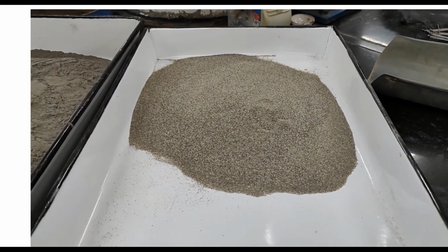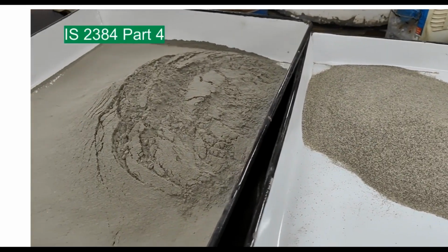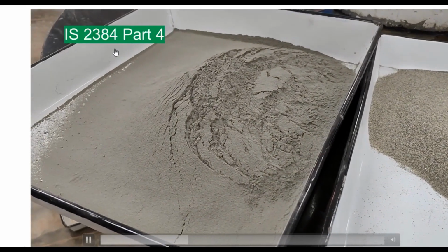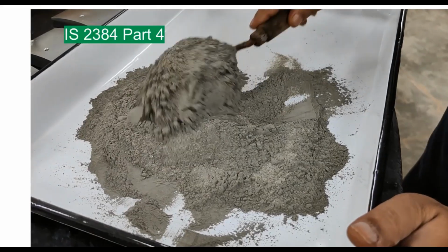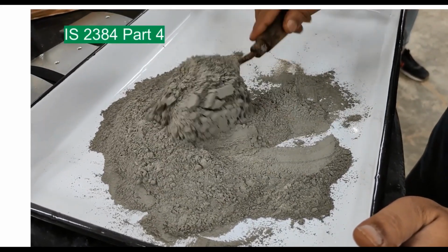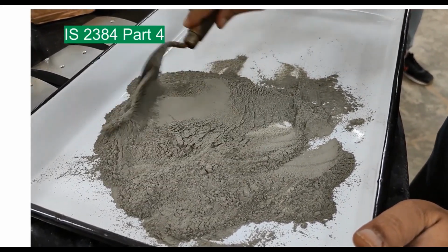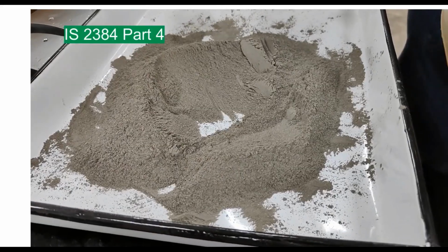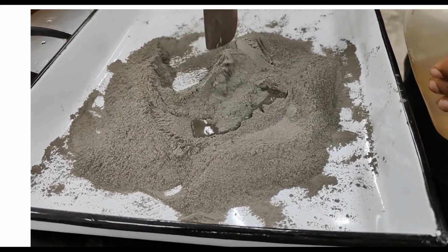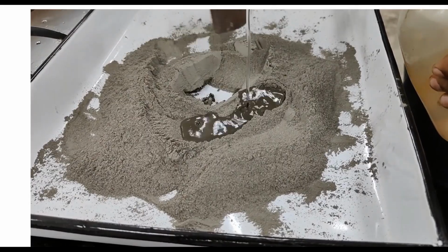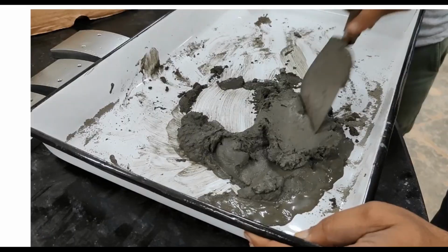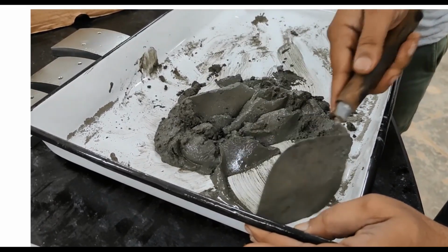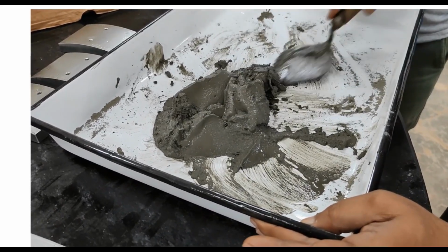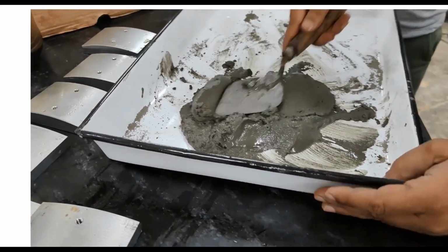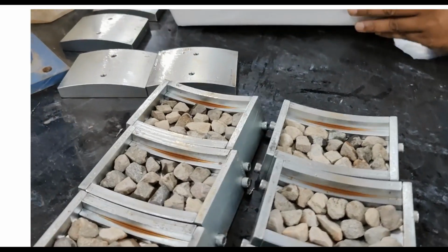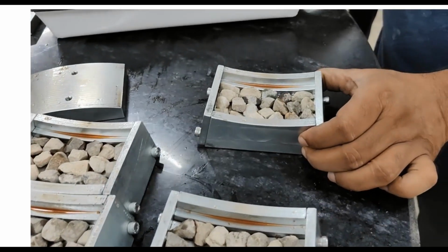If you are making the specimen with cement sand paste as described in IS 2384 part 4, then take equal amounts of cement and sand in the ratio of 1:1. Say you take 300 grams of cement and 300 grams of sand and add sufficient quantity of water to prepare a thick paste. Then spread this paste carefully on the surface of the aggregate in the mold.